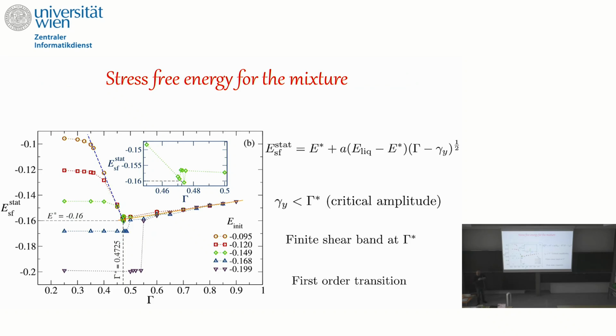So what we said is that we reach this solid, which is very well annealed and independent of the initial condition, and then increasing the amplitude a little bit, you already create a finite shear band. And then what you have is completely independent of the preparation. You have a shear band, which is the liquid, and you have the rest, the solid part, which is at this energy E star.